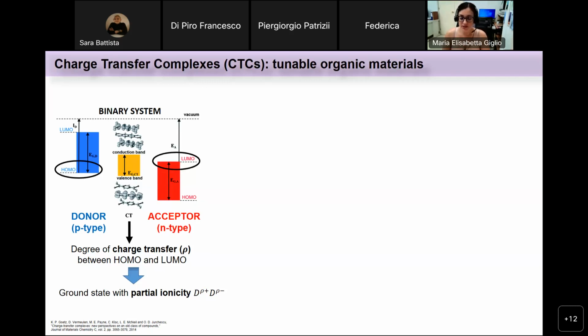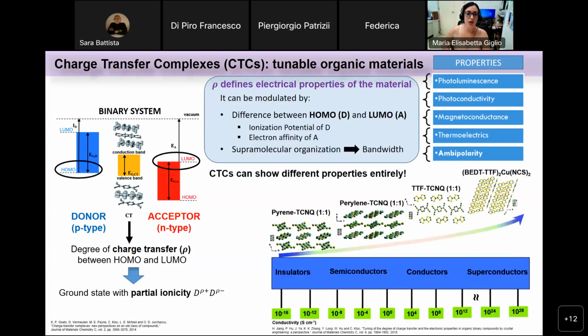And basically, what happens in the binary system is that the electronic coupling between the highest occupied molecular orbital of the donor and the lowest unoccupied molecular orbital of the acceptor occurs. And so this basically leads to the creation of a new energy band of the new complex, with a resulting degree of charge transfer between the HOMO of the donor and the LUMO of the acceptor, leading to a ground state with partial ionicity. The degree of charge transfer is very interesting because it defines the electrical properties of the final complex, and it can be modulated in different ways.